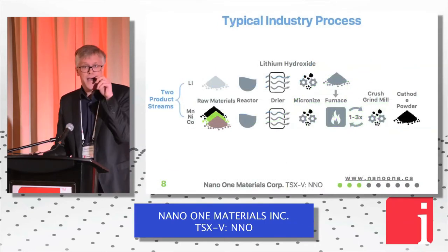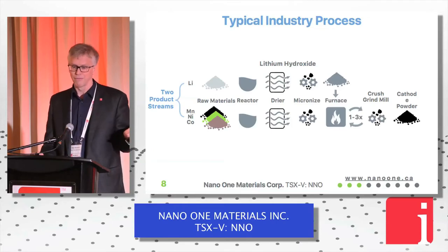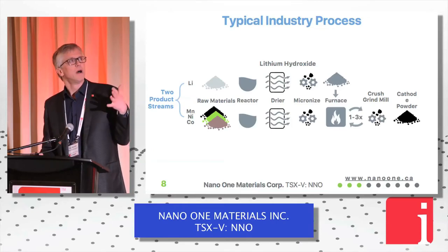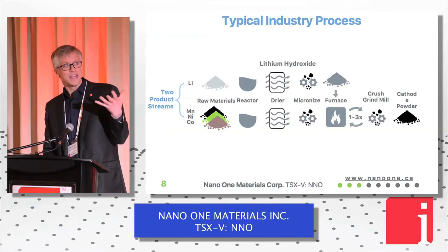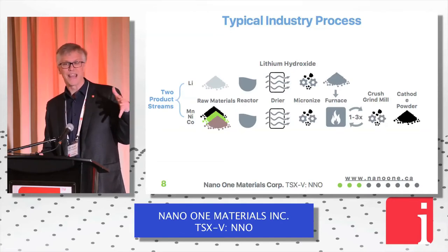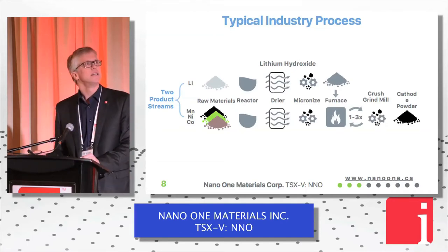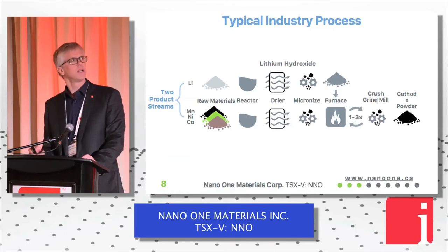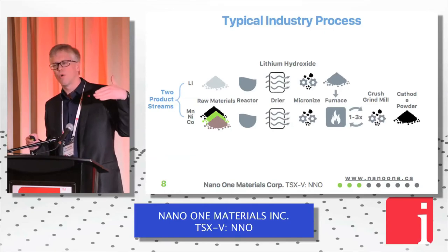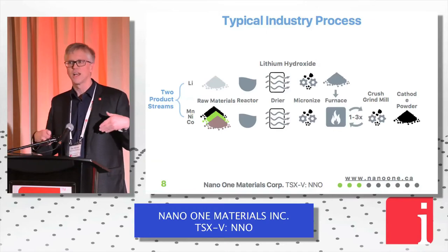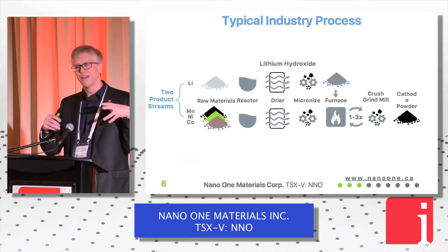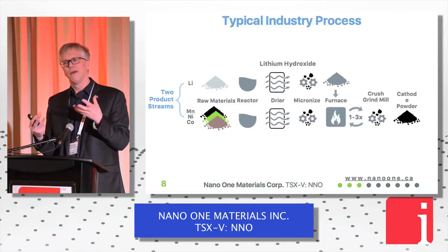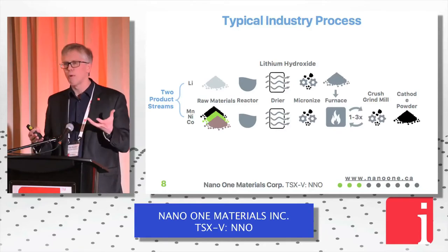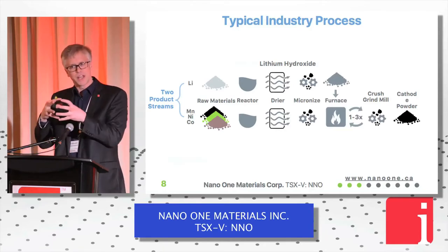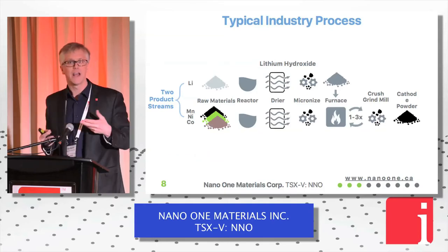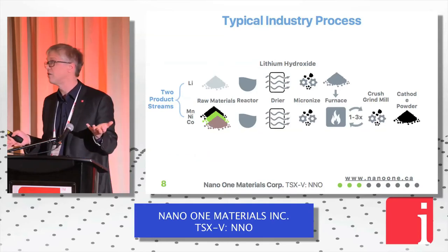So why is that? I'm going to tell you how we make these materials today. The industry typically will take lithium, nickel, manganese, and cobalt, and run them through two different product streams. The lithium can be converted into a carbonate or a hydroxide. It'll get ground and milled, it'll get crystallized, and you get this fine powder out at the end. It gets mixed with nickel, manganese, and cobalt powders, ground and milled, and mixed together so that there's a uniform mix, and then it gets thrown in a kiln or a furnace, cooked at about 800 or 900 degrees.